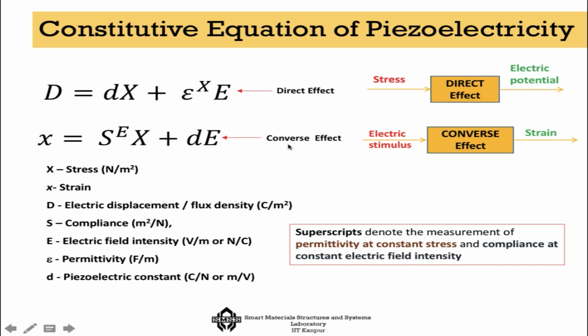Now for the converse effect, you are applying the electric field, not the mechanical field. Mechanical field creating small x, that is the mechanical strain, is quite natural for any material. But you are applying an electric field and finding the mechanical strain, that's something new, isn't it? And that is the basic equation that we will be using for developing these artificial muscles: by applying an electric field, mechanical deformations, and that is the converse effect or the reverse effect, the electrical stimulus creating the strain. Once again here you can see the same electromechanical coupling coefficient. That means the higher the material's d, the more strain I will get out of the same electric field. So these are the two very basic equations which will continuously guide us in the development of actuators and sensors by using these two effects.